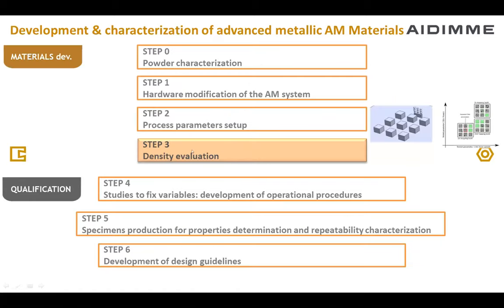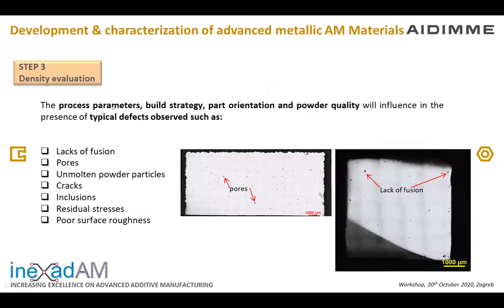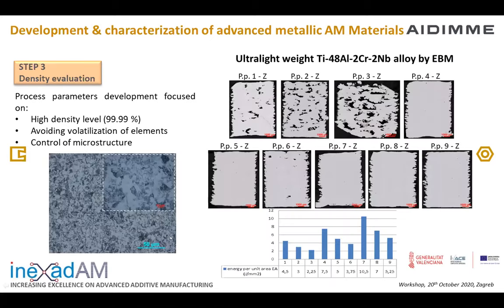So steps 2 and 3 are together. We perform the evaluation together. The process parameters, build strategy, part orientation, and powder quality will influence the presence of typical defects. For example, lack of fusion, small pores, cracks, inclusions, and residual stresses. So the process parameters development should be focused on obtaining high density level, but controlling also the microstructure and avoiding the volatilization of the elements.